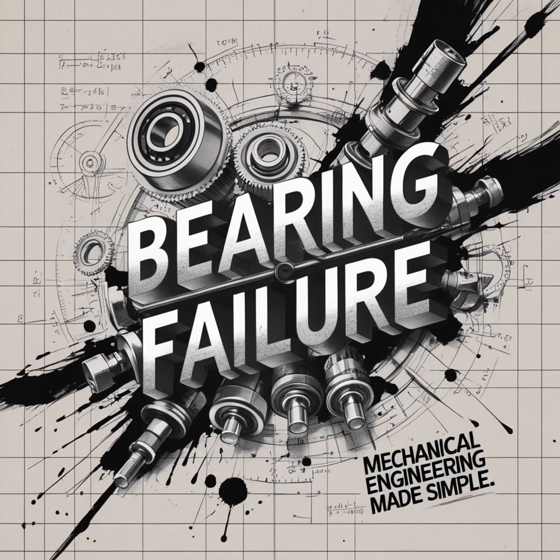And once that ring is deflected, the internal geometry is ruined, isn't it? Correct. The whole internal load distribution changes instantly. So instead of the load being spread evenly, it concentrates in these tiny little areas. And it leads to spalling. It leads rapidly to premature fatigue spalling, which is generally classified under ISO mode 2.2, fatigue spalling.